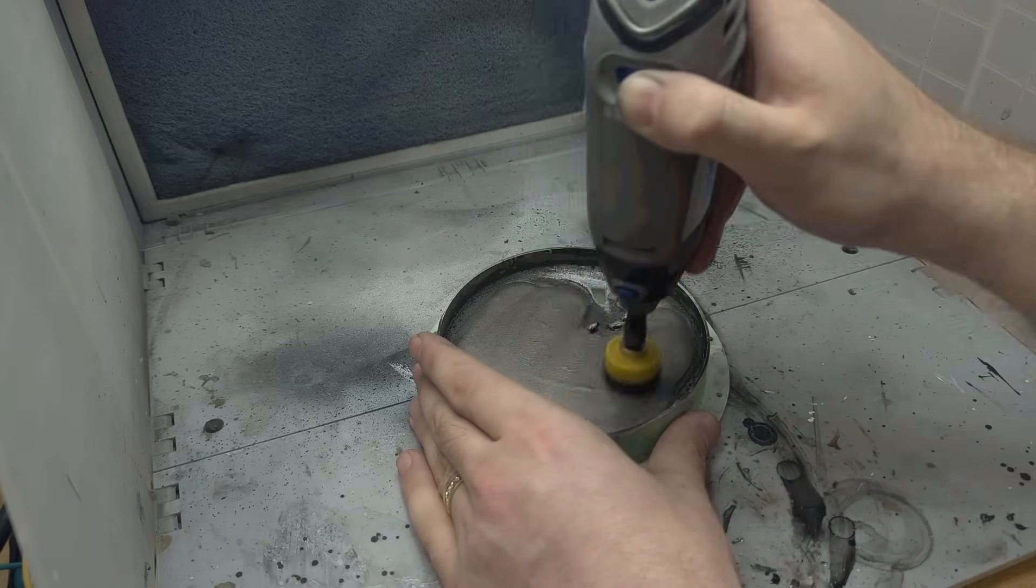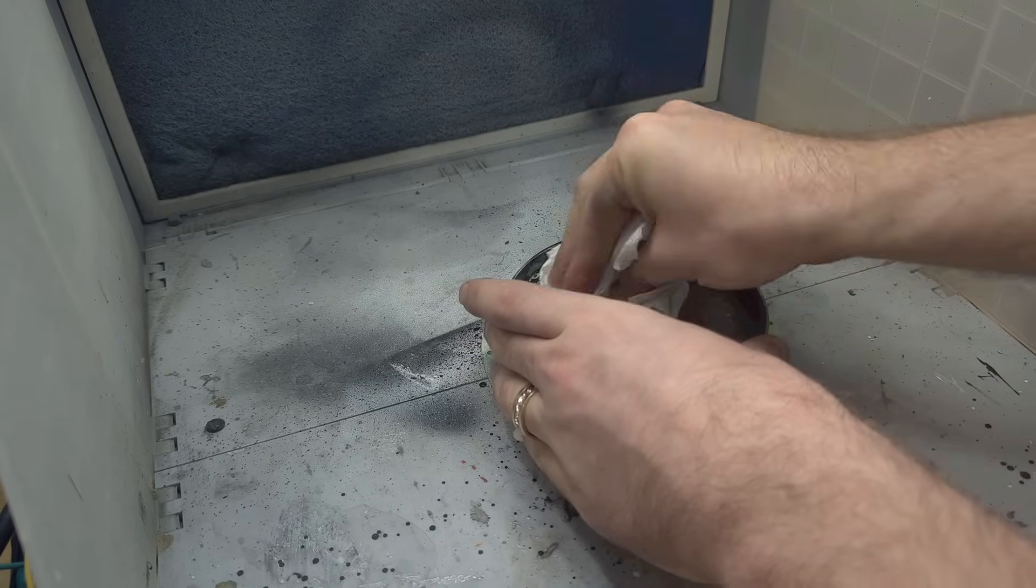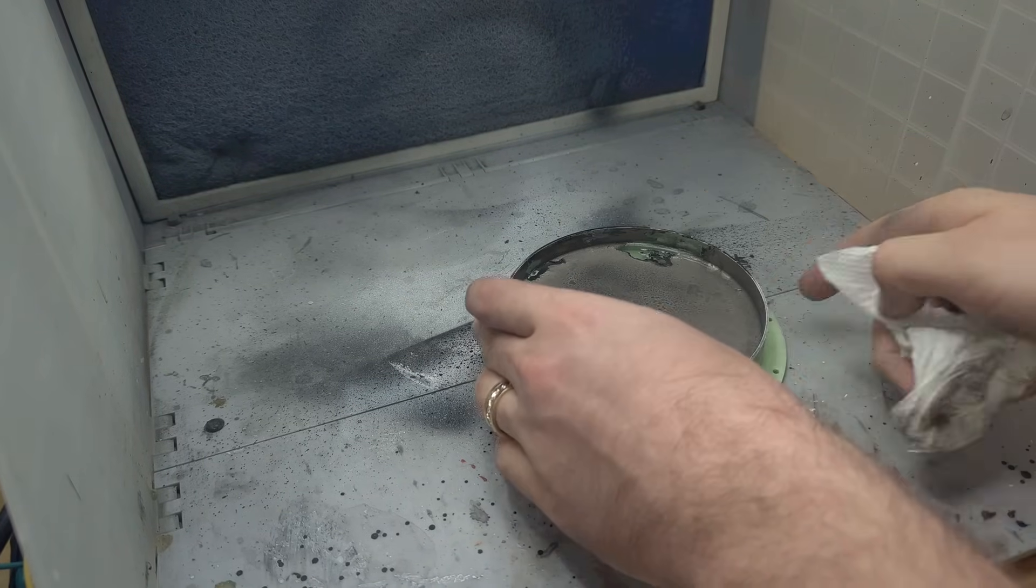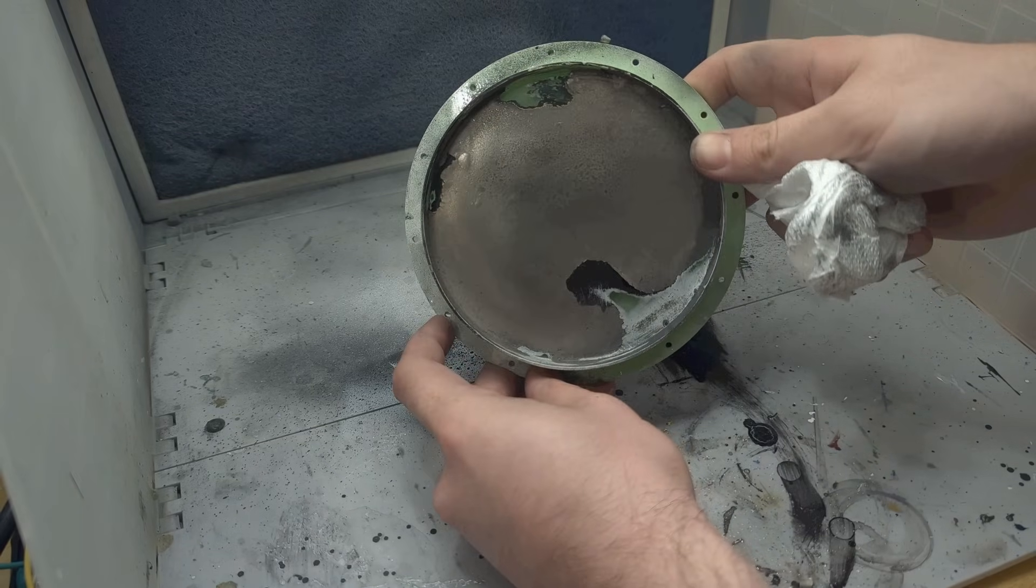After some more polishing, it was clear to me that this roughness was due to the underlying paint, and I wasn't going to be able to get a fully polished mirror out of this. Plus, the metal surface was also beginning to get too thin for much more polishing, and it was starting to flake off near the uncoated regions.